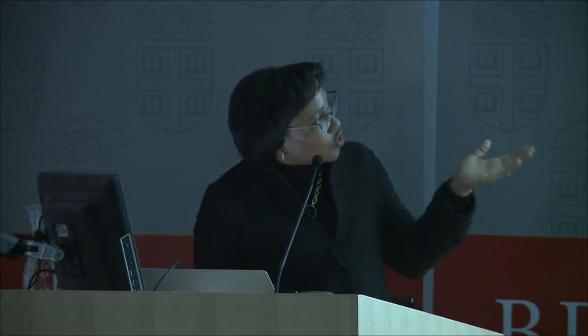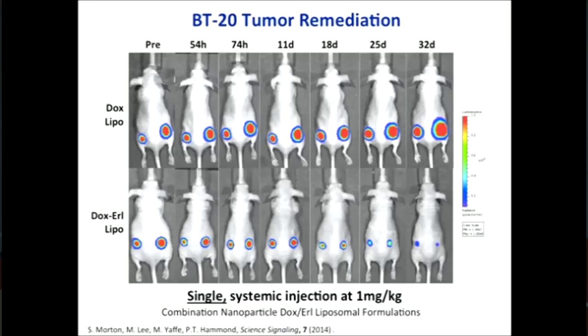So then we took triple negative breast cancer tumors and with a single injection looked at the efficacy of our doxorubicin-containing liposome and our combination liposome, which gives us sequential delivery. And we found a very significant difference. So if you look over time, 54 hours out to 32 days, with just the single systemic dose, we're seeing a huge difference in the regression of the tumor versus its growth in these systems. So we're very excited about this development.